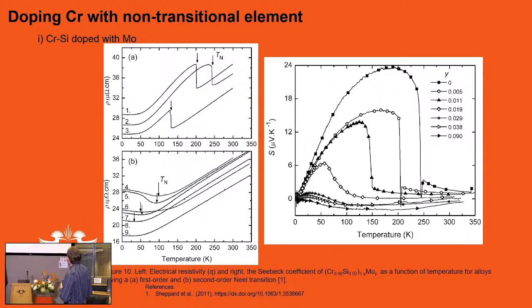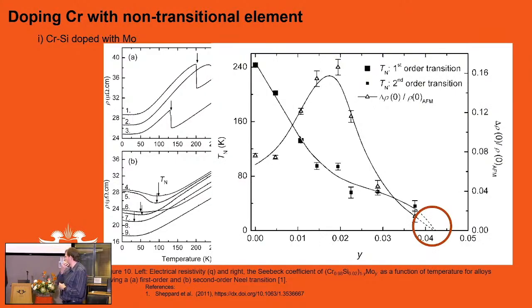But what's the thing here? We do all these experiments, but what are we tracking? We want to track the magnetic temperature to see where you go from this paramagnetic state to an antiferromagnetic state. In this case, so we then go and we plot this after many experiments, many measurements. This only has resistivity on it, but we add the Seebeck to this. We add other measurements to this also. So what we then do is, if I look at this transition temperature, initially it is linear until you see this almost first order to second order transition here. There's a change in this slope. What's on the right here is just the magnetic contribution, in essence, to your material. So how strong is this transition at the end? Which you can see is where this first to second order is.